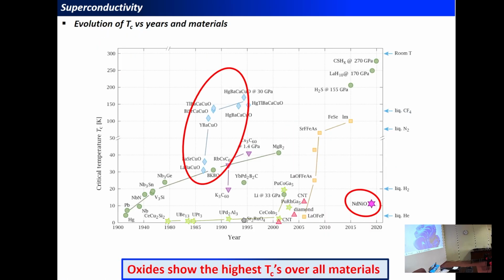If you look at superconductivity over the years, I just borrowed this figure from Wikipedia, the estimation of the critical temperature and the evolution across the materials, we see that the highest critical temperatures reached at ambient conditions, at normal conditions, are observed for oxide superconductors. You have the cuprates, of course, but also the bismuthates around here. And the latest superconductors that have been observed in recent years are also oxide superconductors, which are the nickelates.